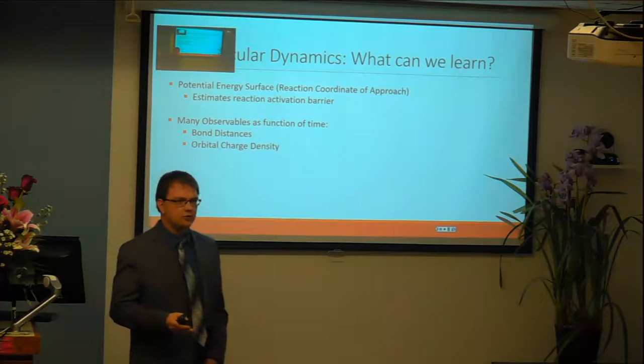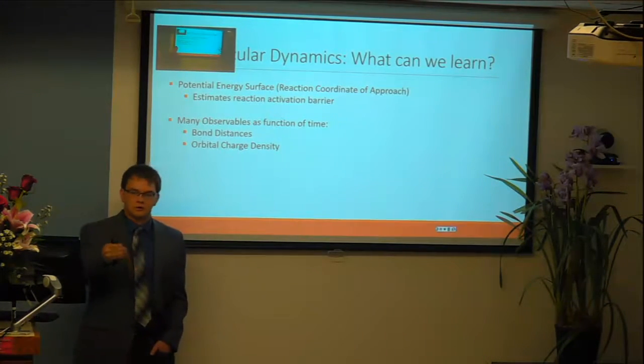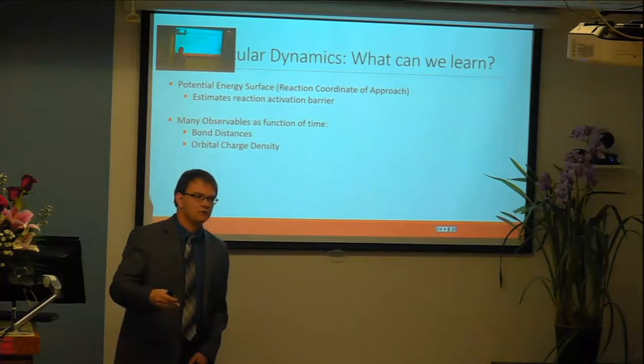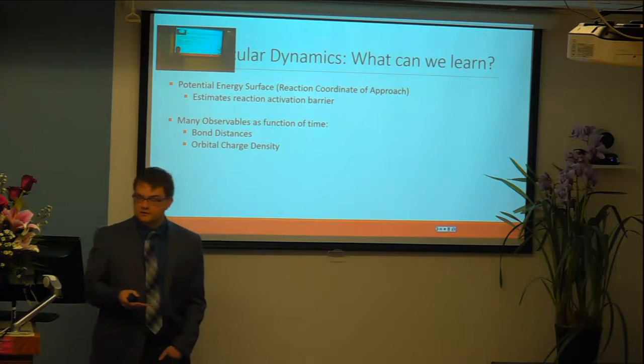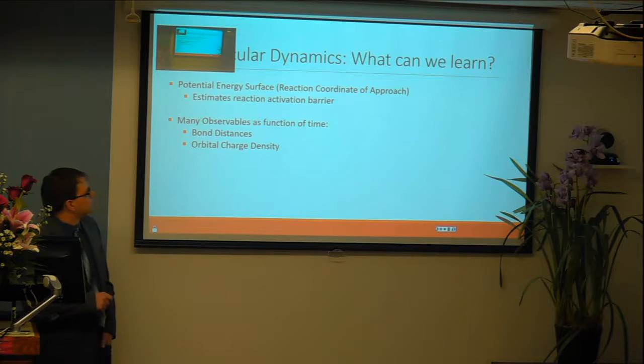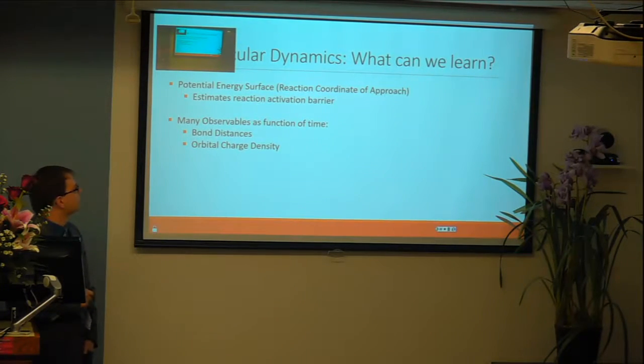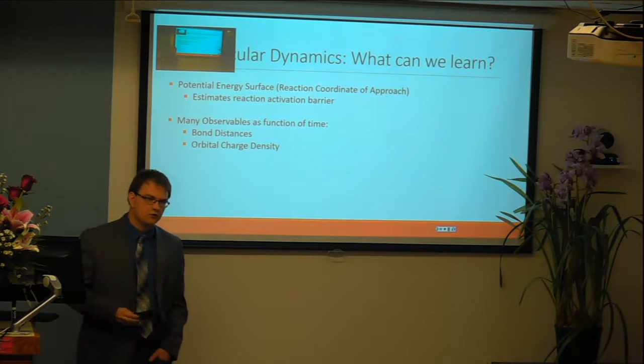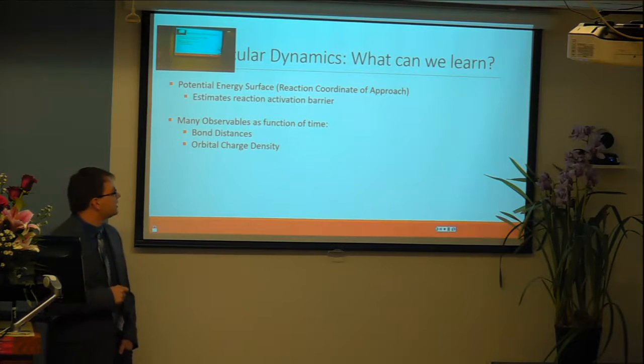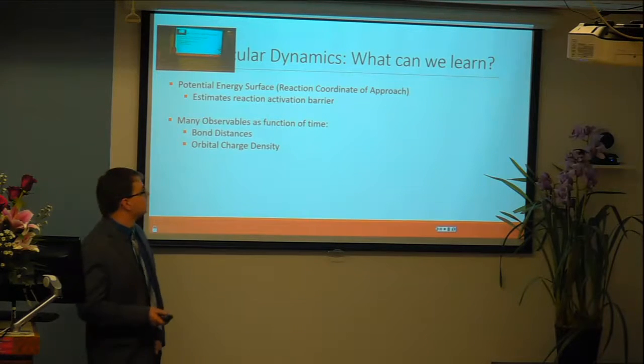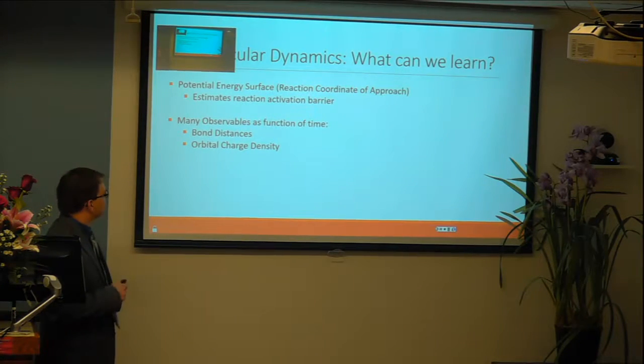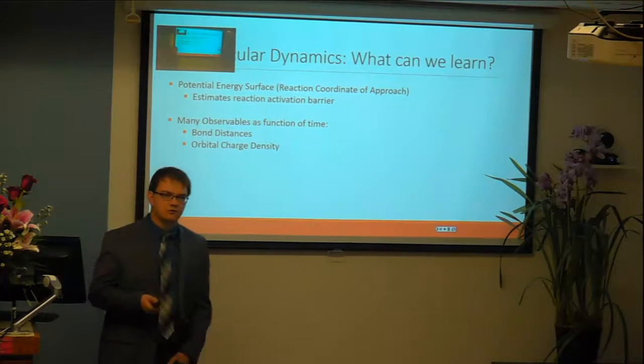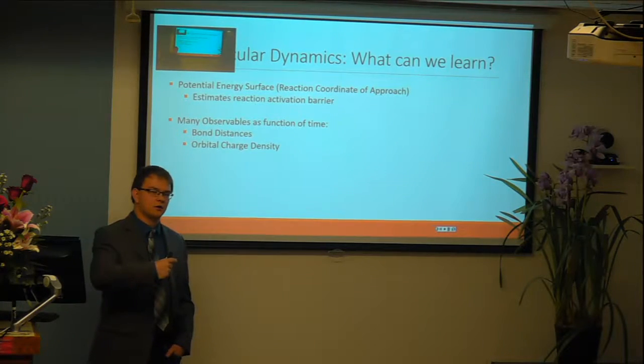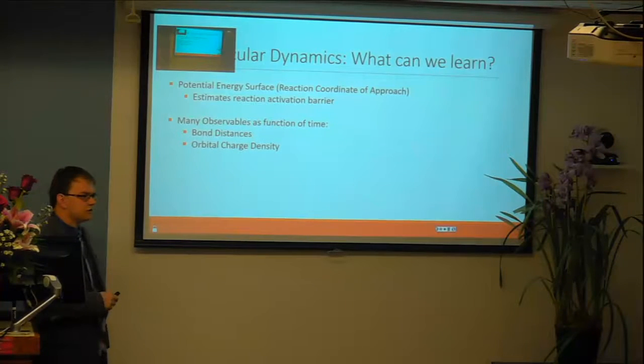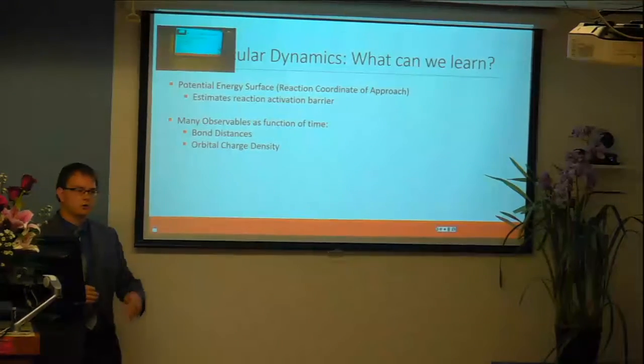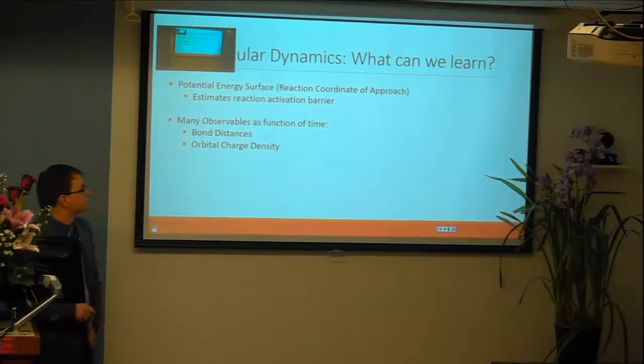More interestingly, we can run dynamics to shoot a chloride ion at the iron, at different angles and different velocities, to simulate how this reaction might progress in nature. The potential energy surface, of course, is very complex, but by picking a vector approach and choosing different velocities, you can estimate roughly the activation barrier for this reaction to occur. Some observables you can look at are the bond distances of different atoms, to see if things are participating in bonds as they evolve in time, and also partial charge density, so the HOMO and LUMO orbitals visualized as a progression of time and their localization.